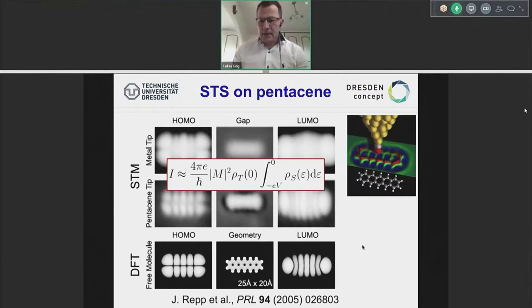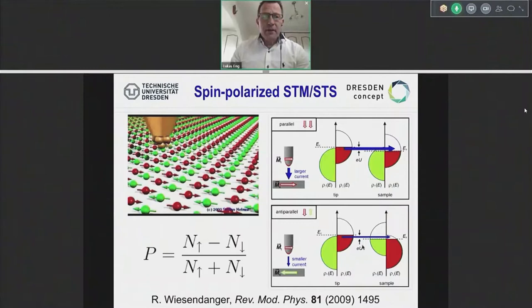Fine. Well, STM is fantastic for that, as you saw. One thing on top of that is spin polarization. Electrons not only have their charges, but they also have spins, like shown here, red and green. And you can do the same trick now by tunneling into a density of states, using either equal orientations or opposite orientations.